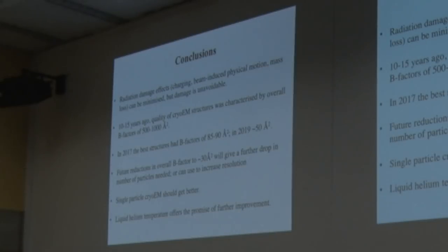So the bottom line then is that the one thing we can't ever fix is the radiation damage, but the effects of it, you can kind of get around them and program around it with computer programs, with better images, with better detectors, and so on. And then 10 or 15 years ago, we were in the blobology era of electron cryomicroscopy, where people said, oh, we don't want that, we want atoms. And the B factors were 500 or 1,000, and that was the limitation. But then the microscopes, the hardware, and so on were improved. And then a couple of years ago, we were at B factors of about 100, and people were very happy. But now it's down to 50, 60.